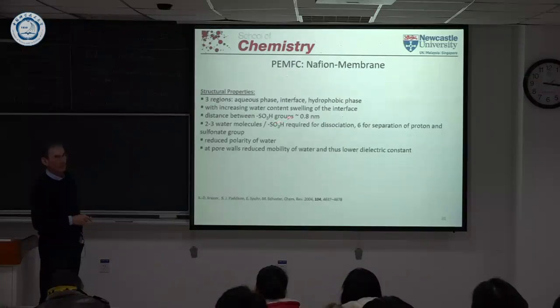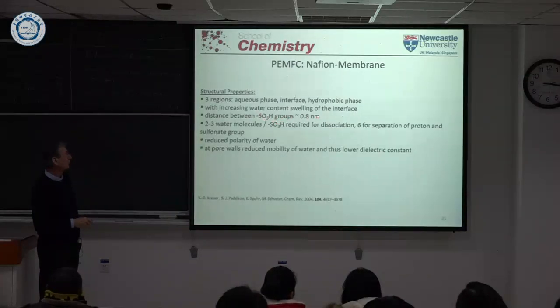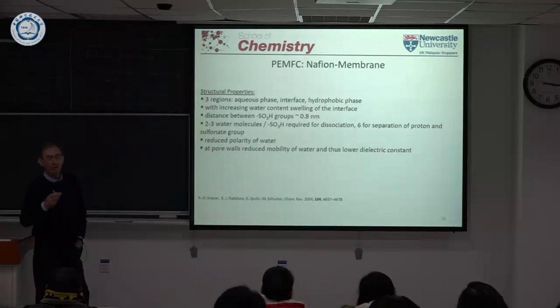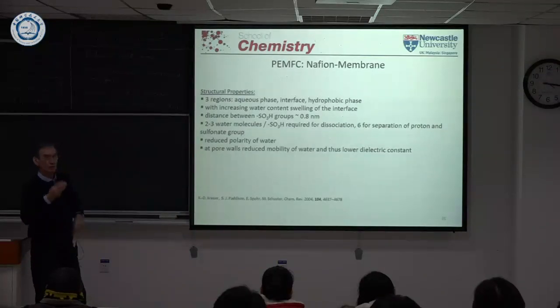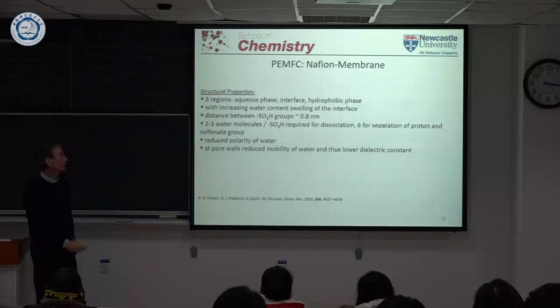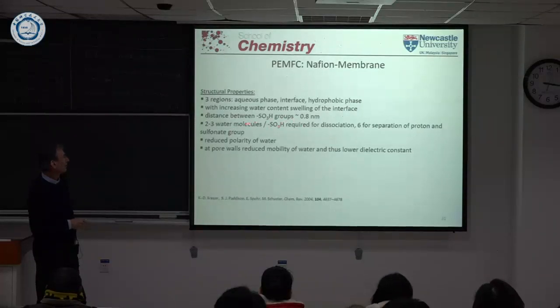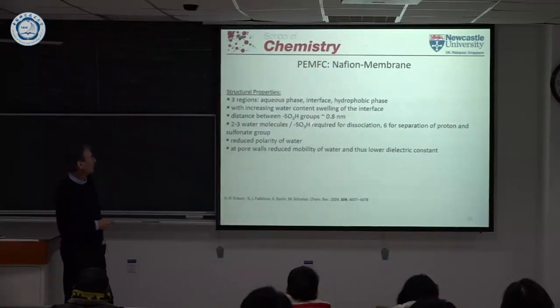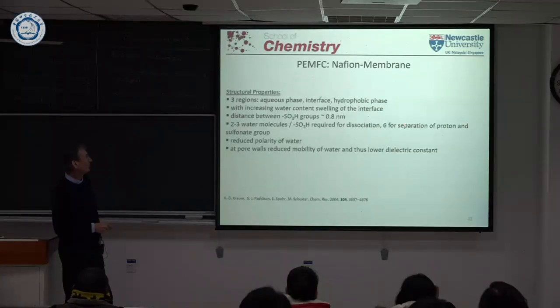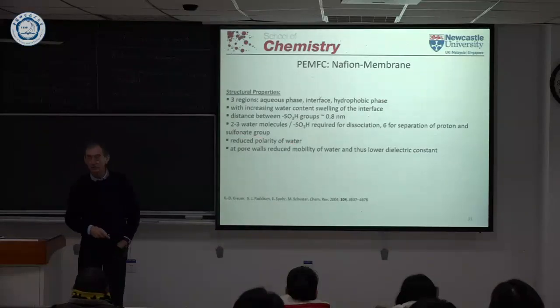Then, depending on the number of sulfonic acid groups, you can say what the distance between these sulfonic acid groups is. It's about 8 angstroms. So that means actually there are a lot of sulfonic acid groups on the surface of the polymer. And you need about 2 to 3 water molecules to get a dissociation of this proton from the sulfonic acid groups. And then you need a total of 6 water molecules for separating the proton from the sulfonic acid groups.